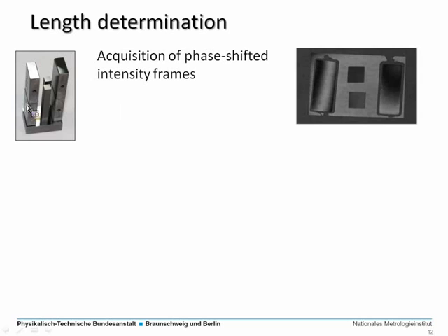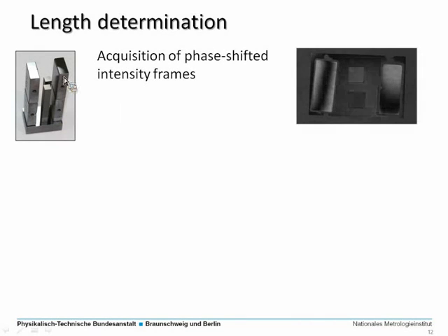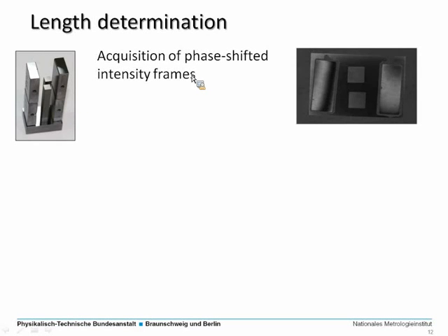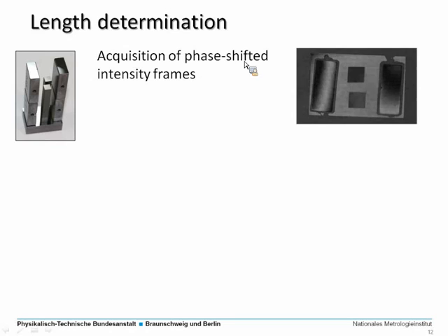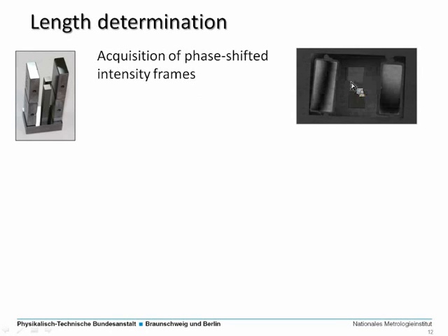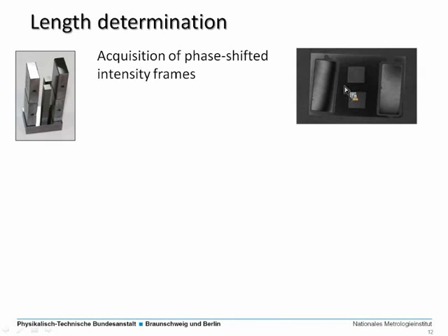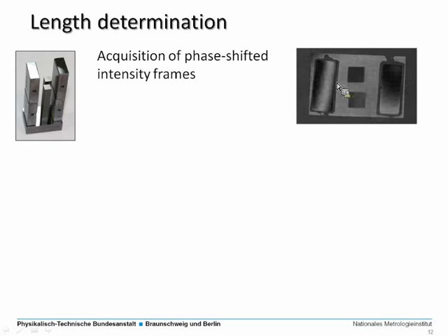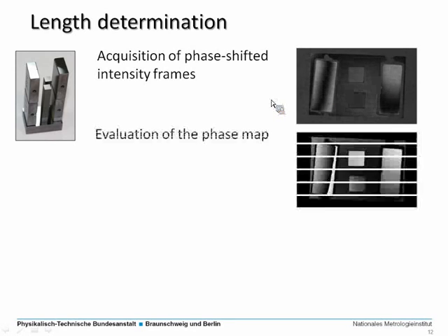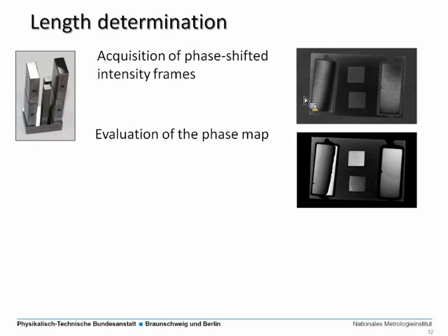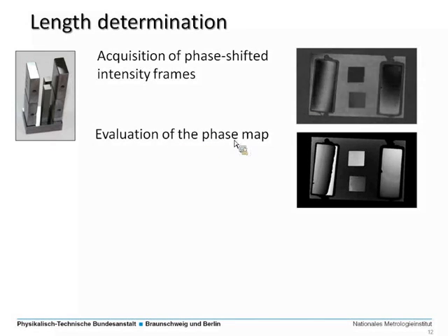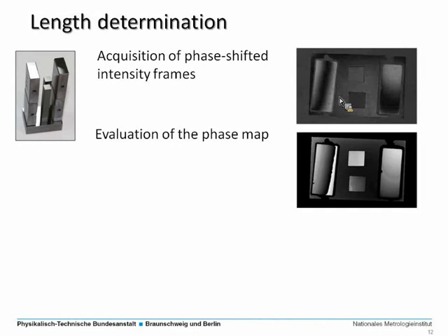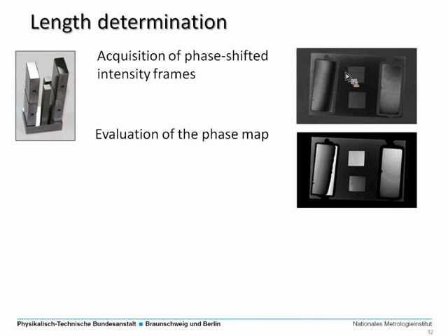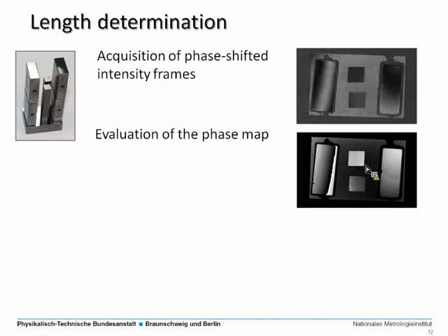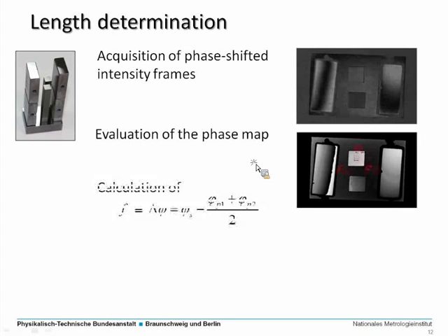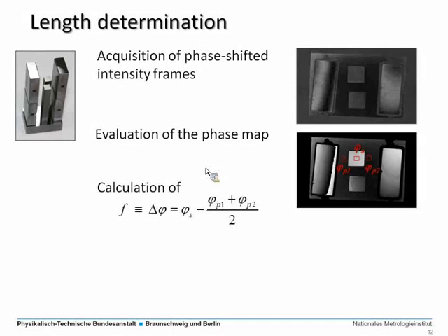Here is another example from reality for this sample arrangement with different gauge block shaped materials. At first you acquire these phase shifted intensity frames. This is shown here on the right hand side. You see a series of frames in the same picture. You can use these phase shifted images in order to evaluate the phase map. For this evaluation, not the Carré algorithm was used, but a different one, but the result should be the same if you apply it properly, depending on the measurement procedure.